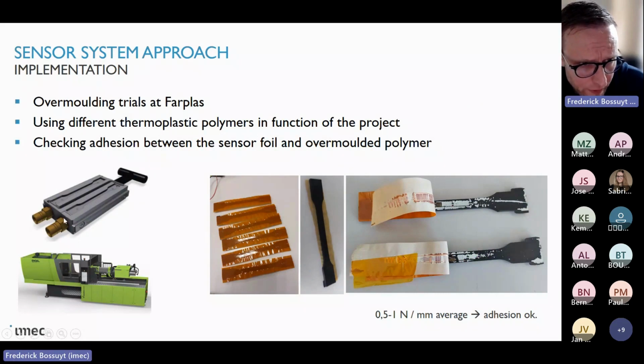During the project, we have already done quite some overmolding trials at Farplas, using in the project different thermoplastic polymers. Recycled polymers are used. These overmolding trials have been performed on our foils to mainly check the adhesion between the sensor foil and the overmolded part, because it's important to have a good adhesion for making sure your sensor is capturing the strains. So here you can see we have a good adhesion, about half to 1 Newton per millimeter on average. It's still possible to separate the two. So also in terms of recycling, we can still remove the foil.